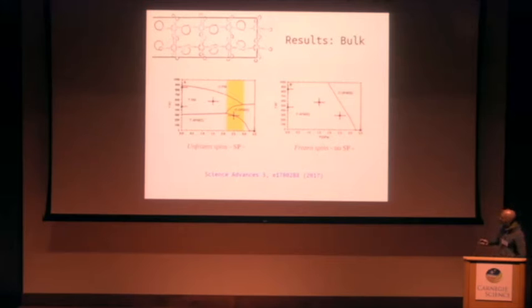Basically, these crosses and points are experimental data, and these lines are our predictions. So if you consider zero pressure, this is pressure and this is temperature. At zero pressure, with our approach, we could quite accurately predict the phase transitions at the points where experiments get them, right? One important thing is that if you don't consider this approach, in which you take into account the effects of spin disorder, then you never get these transitions right as in the experiments. In principle, you get some transition temperature that is just unphysically high.